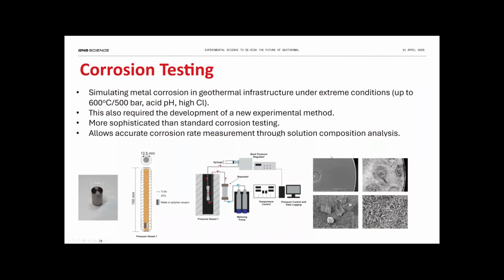Another important thing that we can simulate is corrosion testing. Our current capability is up to 600 degrees, 500 bars. We can do extremely acid pH. We've done down to pHs of 3 and up to 10,000 parts per million chloride. We can do up to 600 degrees.